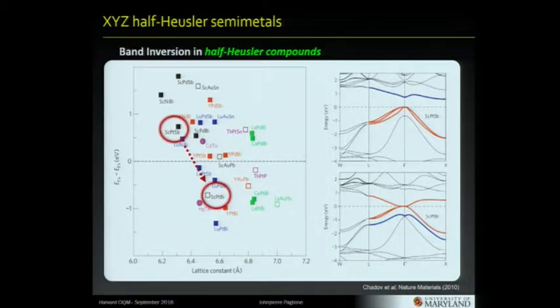No, that's not true. But there were a couple of back-to-back predictive papers showing essentially the calculation of the electronic band inversion in this family of half-Heusler materials, or at least some subset of them. They showed that depending on the spin-orbit strength, some materials have a trivial band topology and some have an inverted band topology. There's a nice example here where you just change scandium platinum antimony to scandium platinum bismuth. That actually tunes across this crossover line, and you go from a trivial gap system to an inverted band gap system.